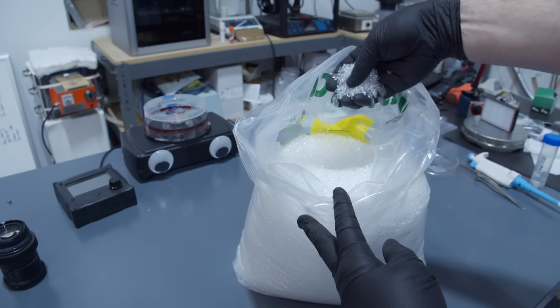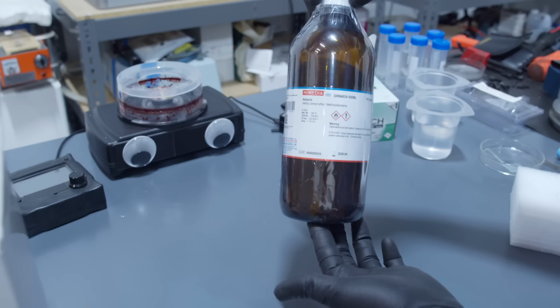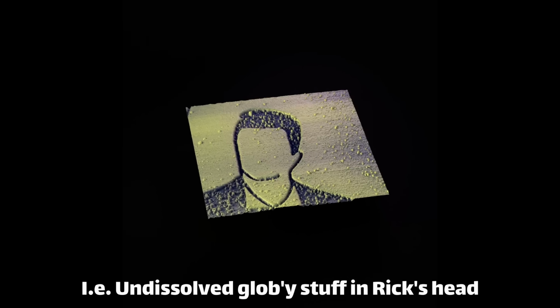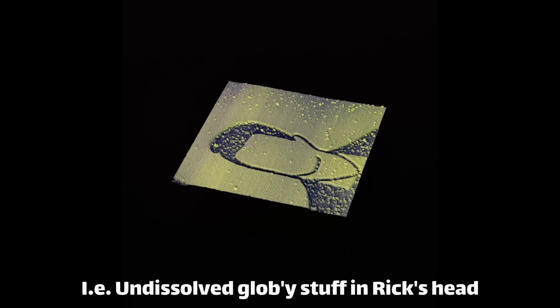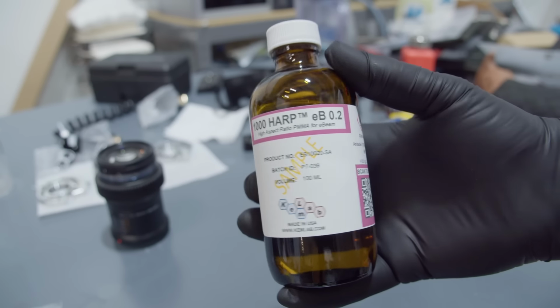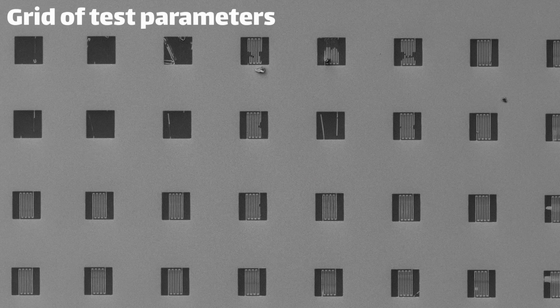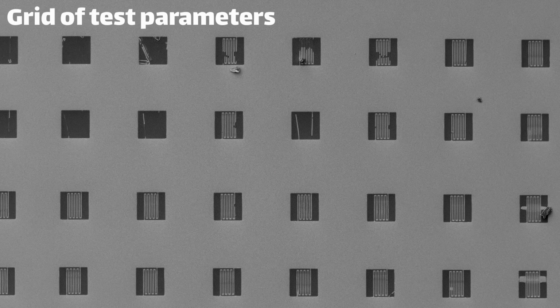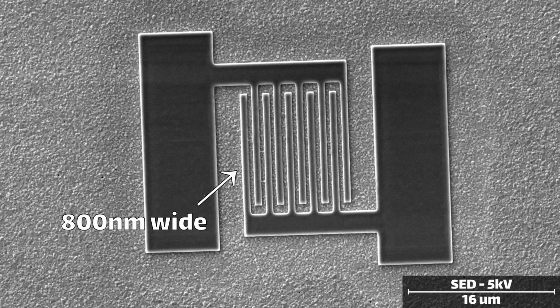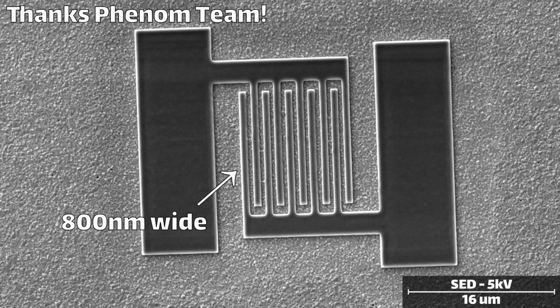In the original video, I used acrylic injection molding beads dissolved in a solvent. My DIY resist worked okay, but it wasn't ideal and led to some problems. So to make things easier for me this time around, I purchased some real PMMA resist from a lithography vendor. I've also been working with the R&D team at Phenom to improve the Python API that controls my scanning electron microscope. The folks at Phenom have added a new patterning API, which offers a lot more control of the process and has helped immensely. So between these two improvements, I've been able to pattern some very small and pretty crisp electrodes.